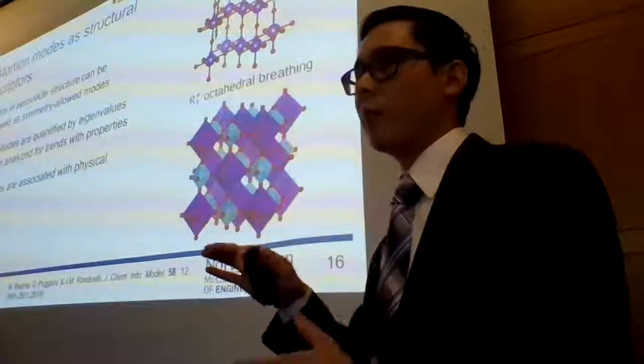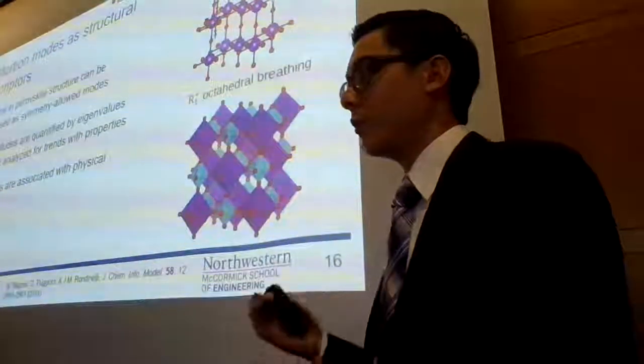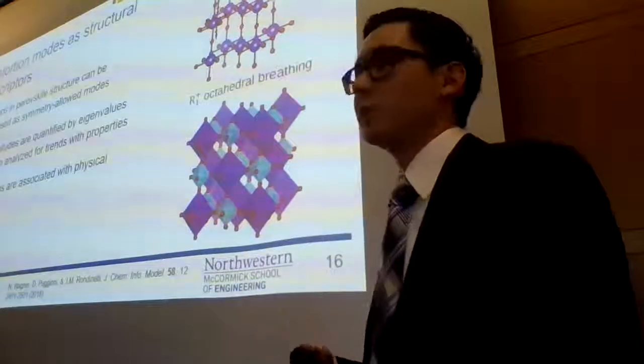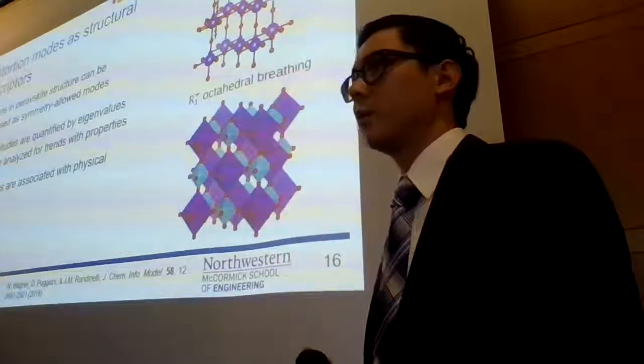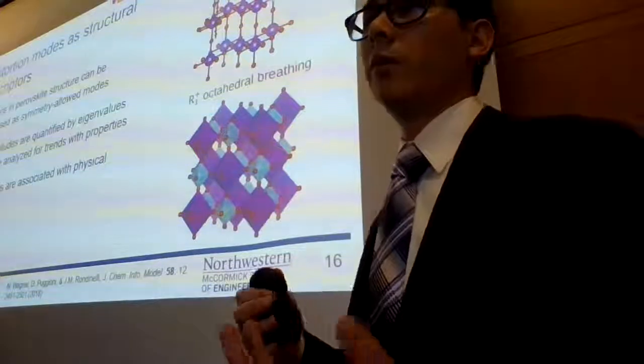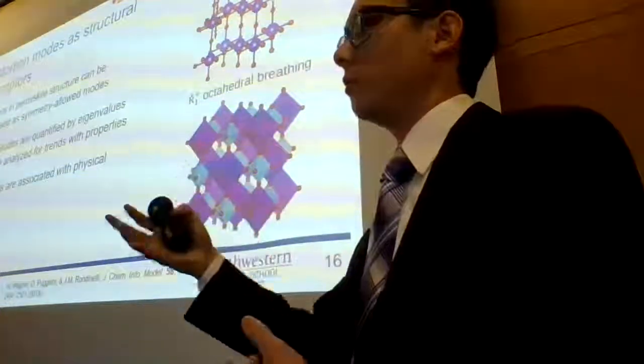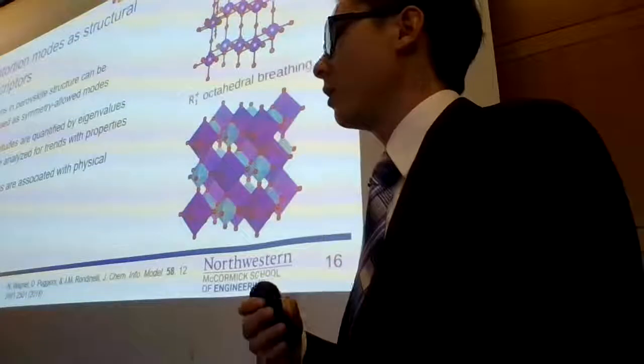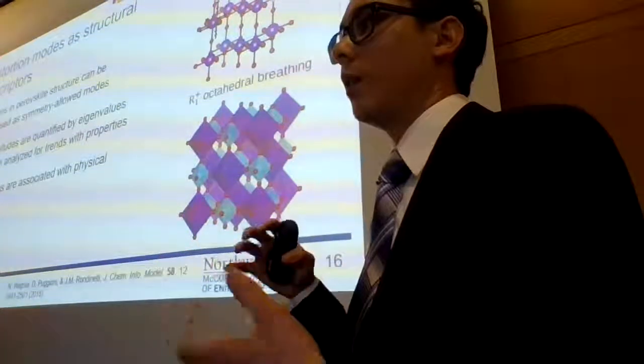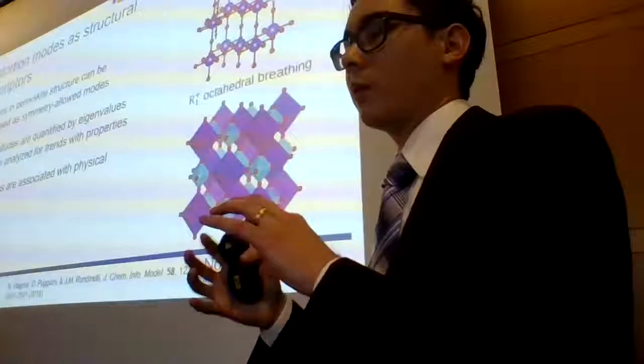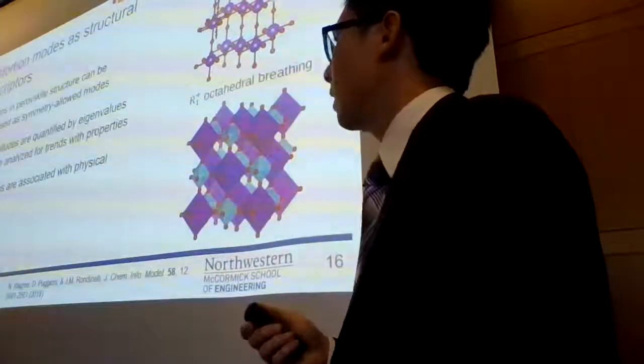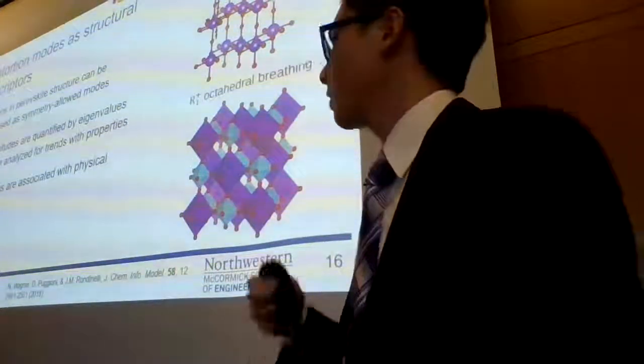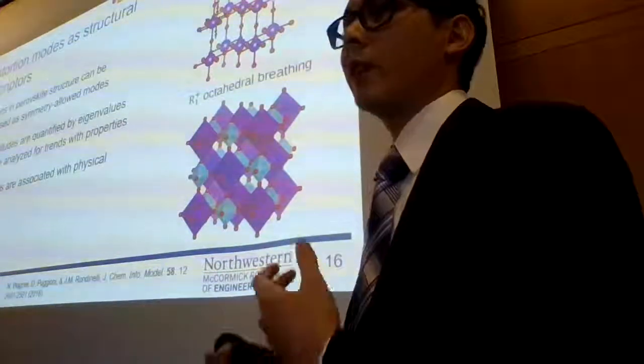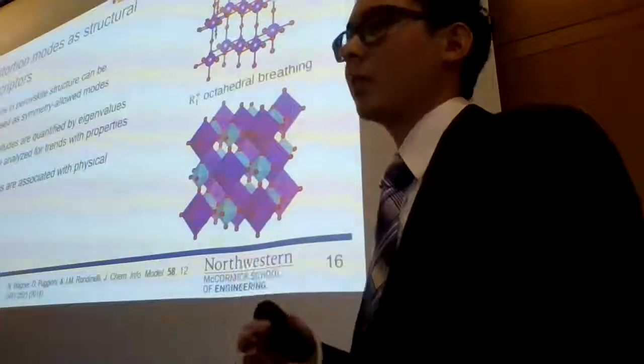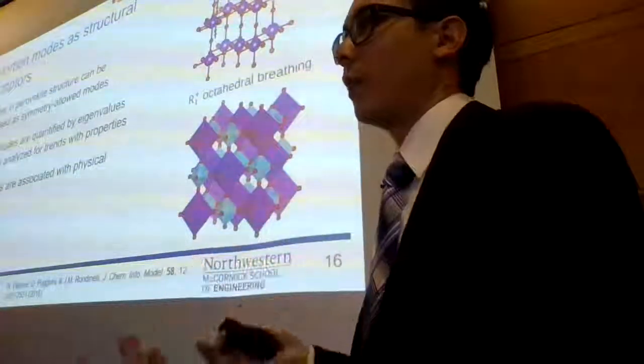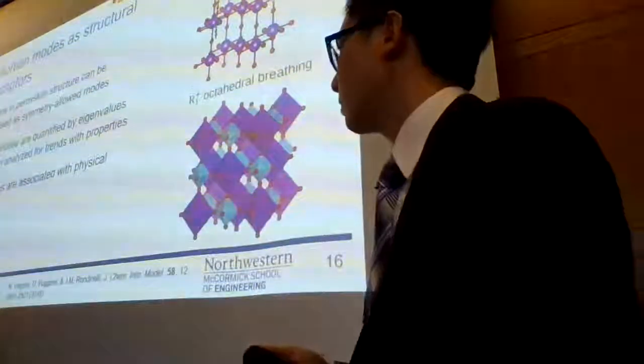So that phase diagram is one way to visualize this family of materials, but another way you can think about visualizing them is in terms of distortion modes, symmetry adapted distortion modes. As the structure goes from, say, a hypothetical high symmetry cubic phase down to an orthorhombic or monoclinic phase, there are a set of symmetry allowed cooperative displacements of the atoms that can be quantified using group theory and assigned labels. You could think of that as another quantitative way, instead of just the tolerance factor, to quantify the distortions of these materials.